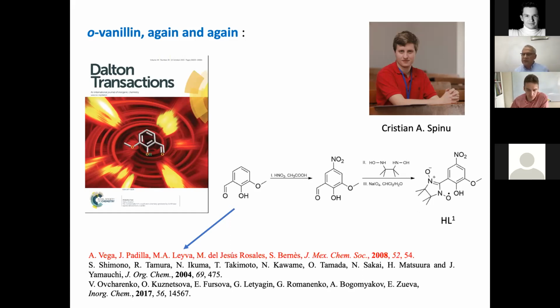The only information existing in the literature, the one indicated here in red, gives an idea about the existence of this molecule that was never employed as a ligand. Moreover, the yield is very low. So in order to improve the yield, we blocked the para position with respect to the OH group, and we were able to obtain good yields. This radical was employed by Professor Ovcharenko in his group for the first time in 2017 in designing some cobalt complexes, and the synthetic procedure was reported in 2004.